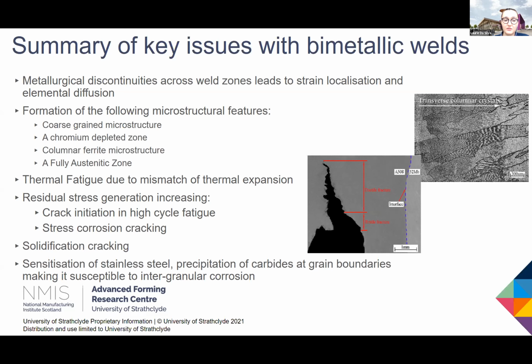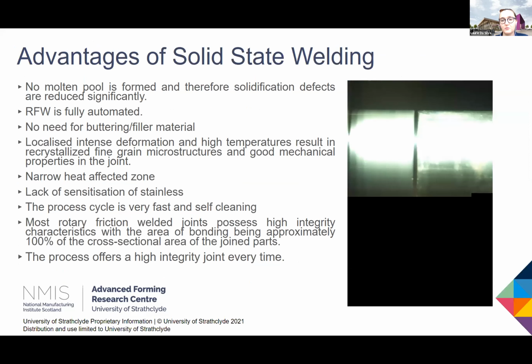You can also have general solidification cracking from solidification of the melt pool, as Richard discussed. And you can have sensitization of the stainless steel, which is essentially precipitation of chromium carbides around grain boundaries, making it more susceptible to intergranular corrosion. So all of that we prefer to avoid if possible.